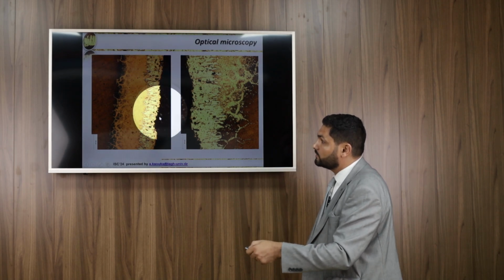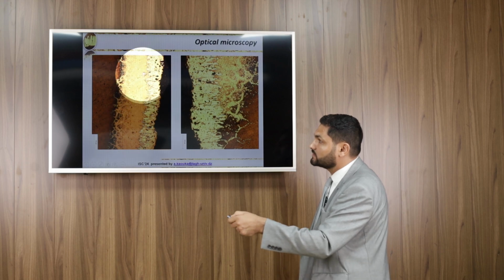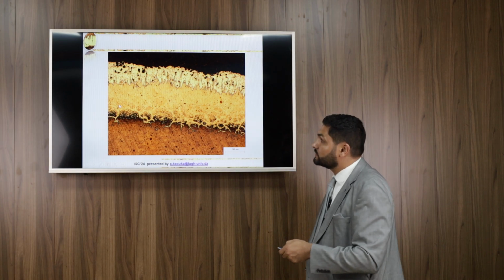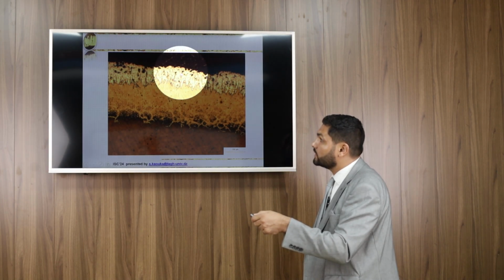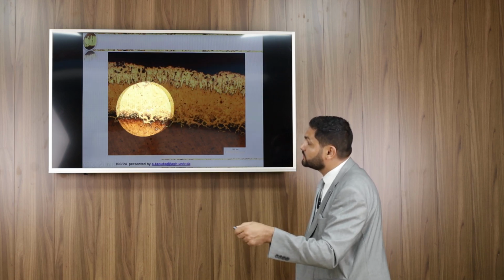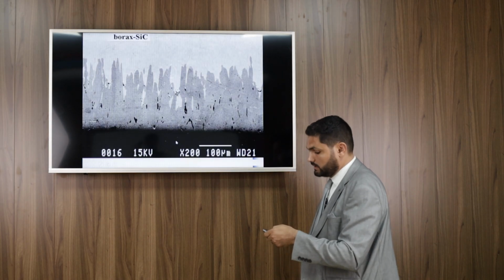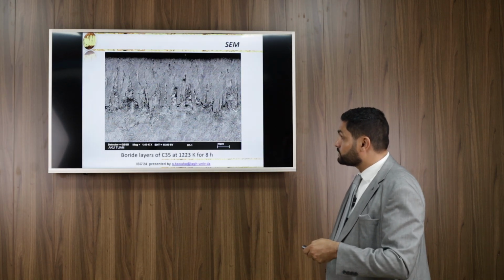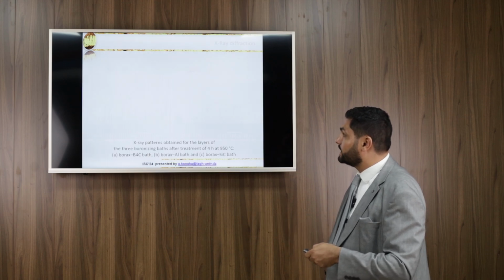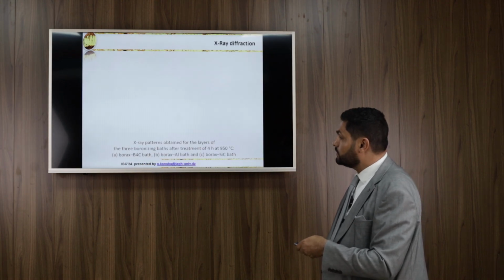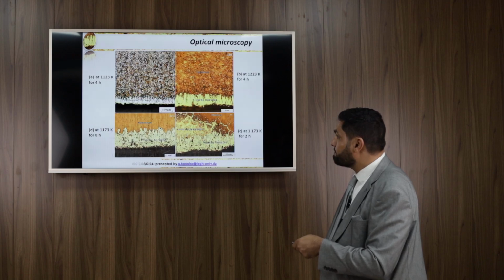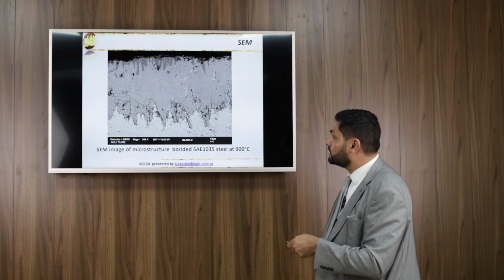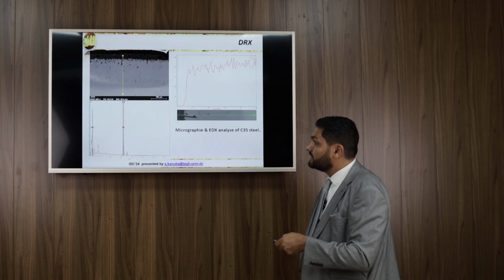As you see here, this is the boride layers. This is boride layers formed, and this is the transition zone. The others is just the substrate, as you see here. Here is the same: boride layers, saw-tooth structure, and this is the transition zone, and this is the substrate. After that, the same when we increase temperature. This is the transition zone, this is the boride layers formed, and this is EDS.